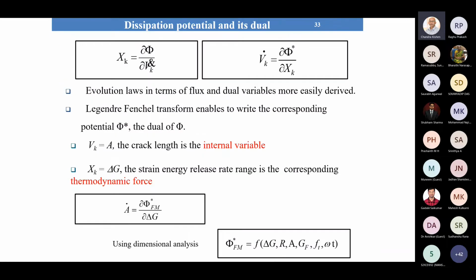So we have developed a relation. What we need is to get the rate at which the crack grows, A dot. Here we need a potential. A potential function is required, and this potential function is available in the literature. Some empirical relationships are present, but here we thought we will make use of dimensional analysis to obtain the relationship of this potential from first principles, using all the factors which contribute to it. That is the force parameters, the loading parameters, which are contained in this delta G, that is the energy release, and the R, the resistance.